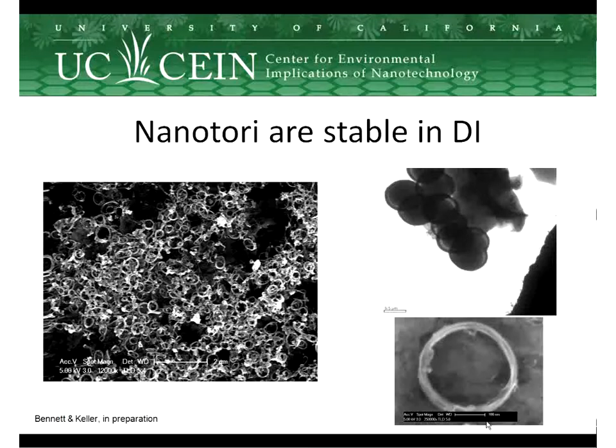So this is about 100 nanometers there. We measured that it was about 150. And if you take the circumference, it coincides with the mean size of the tubes. That's where we are estimating that it is one tube that comes around and wraps around. It has to be a bundle, because this is about, I think, 30 nanometers. So it may be a few tubes that are bundled together.